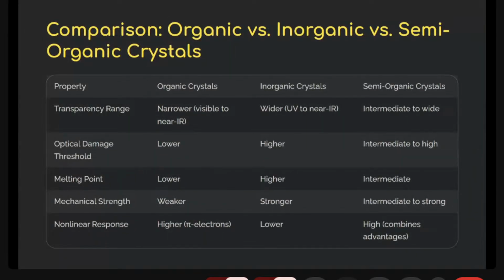So there are many properties which we need to understand while making organic crystals as well as inorganic crystals. In case of transparency range, organic crystals are narrower, visible to near infrared, and inorganic crystals are wider, UV-visible to near infrared. But optical damage threshold is lower for organic crystals, so we cannot use a high power, highly intense laser for them, whereas we can use a high power laser for inorganic crystals. So if we use a high power and highly intense laser, temperature effects come into play.